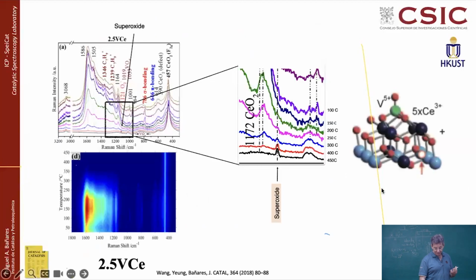which is vanadia ceria. And you remember that vanadia ceria resulted in a strong interaction that results in a very stable cerium-3 plus ion that you never reoxidize. So that's why even at 400 plus, you get superoxide species and they remain there, because it cannot oxidize that cerium because of the neighboring vanadium. So that's why you get the superoxide, which is stable at 450, which usually people see below 0 degrees.